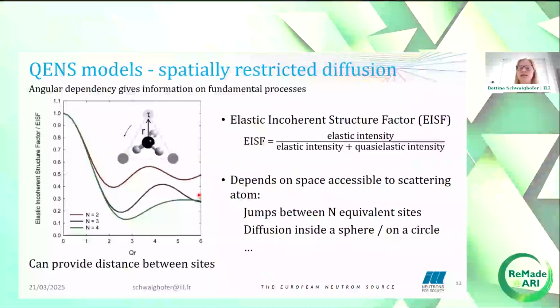If the diffusion is local, so spatially restricted diffusion, the half-width at half maximum will not show a very strong Q dependence. However, in this case, we can use the elastic incoherent structure factor, or EISF, and its angular dependence to extract information about the localized dynamics. The EISF is the ratio of elastic intensity to elastic plus quasielastic intensity. It depends on the space accessible to scattering atoms, and there are models for jump diffusion between different numbers of sites, which is shown in this plot here.